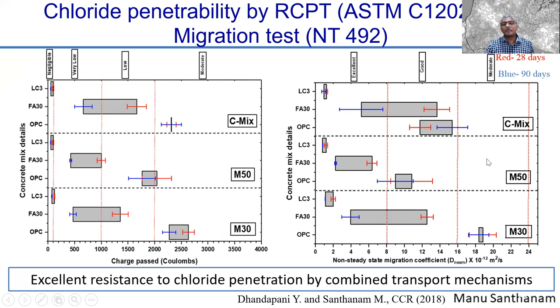Now, if you do a comparative study with this rapid migration test, okay, which is as per the Norwegian standard NT492. So in this test, what you see is the non-steady state migration coefficient that is plotted on the x-axis. You see that for the OPC mixes, you have fairly high values. Fly ash is intermediate. And for LC3, you get very low levels of non-steady state migration coefficient. Those of you who are familiar with this test will realize that getting a value of less than 2 into 10 power minus 12 is generally possible only with silica fume based high performance concrete mixes.